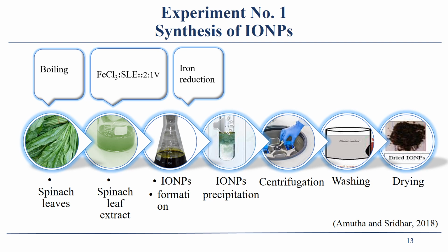For this purpose, spinach leaves will be collected and washed. The leaves will be air dried at room temperature and will be ground into fine powder. Spinach leaf extract will be produced by boiling 5 grams of powdered spinach leaves in 100 ml of distilled water with continuous stirring for 20 minutes. The mixture will be cooled to room temperature and will be subjected to centrifugation at 6000 rpm for 15 minutes to get the aqueous leaf extract.